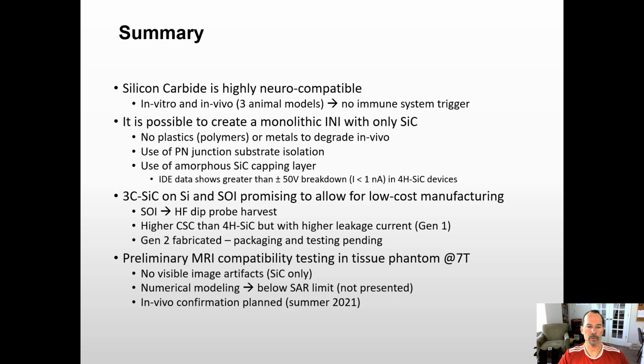Was quite impressive. We've now translated that hexagonal silicon carbide work to cubic, as shown here. We've been able to easily harvest our device using an HF dip. We had higher charge storage capacity than 4H, but we did have higher leakage current in our first generation cubic devices. Now we're working on Gen 2. I showed you the image before, and it's awaiting final DRIE probe definition, etching, and packaging and testing. And our preliminary MRI compatibility data is extremely encouraging at 7 Tesla.